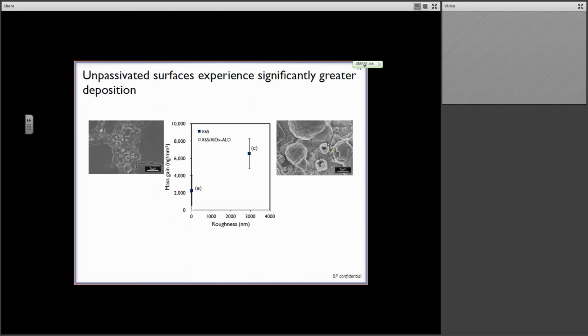On the surfaces that started much rougher, so this micrograph corresponds to this data point here, much rougher, about 3 microns of average roughness, we have a very different morphology on the surface: very large globular structures, which are in fact hollow. If we look elsewhere, we do see some sort of continuous deposits, but there are fewer. We see more of these sorts of deposits here. And so the mass gain on rougher surfaces is much higher. Right, so this kind of corroborates our earlier observations on the effect of roughness, and this gives us some interesting insight in looking at the morphology. We'll get into more of that on the next slide.